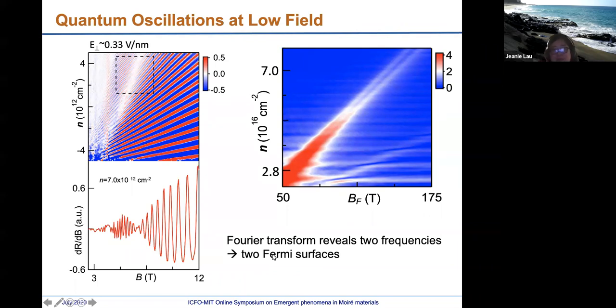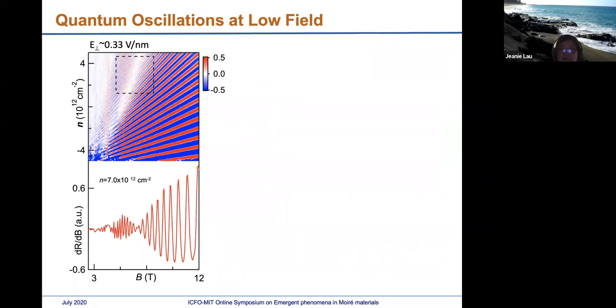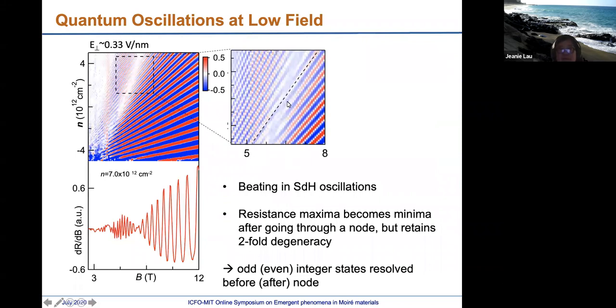So what are the 2 Fermi surfaces? Since this is indium selenide, we actually do not have valley. The only candidate is really spin. So basically, we have spin splitting in this case, but it's not just your normal Zeeman splitting, because with Zeeman splitting the degeneracy should change from 2 to 1, but we actually retain the 2-fold degeneracy in either case.